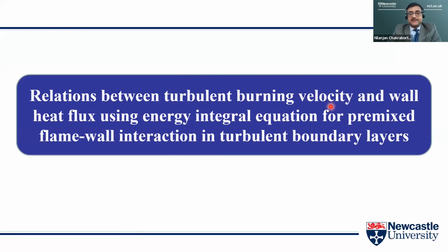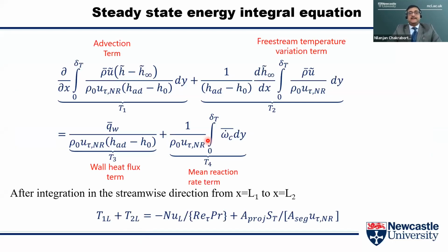we will talk about the interrelation between turbulent burning velocity and wall heat flux using energy integral equation. So those of you who have taken convective heat transfer courses have already seen this equation several times, but here we have an extra term which comes because of the mean reaction rate. And in this case, H stands for sensible enthalpy. And once you integrate these terms between two locations in the streamwise direction, one gets this equation.